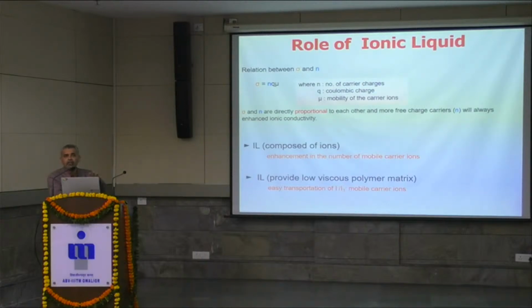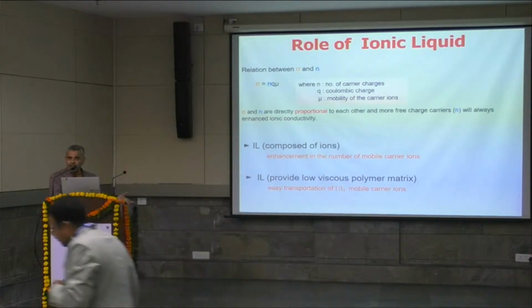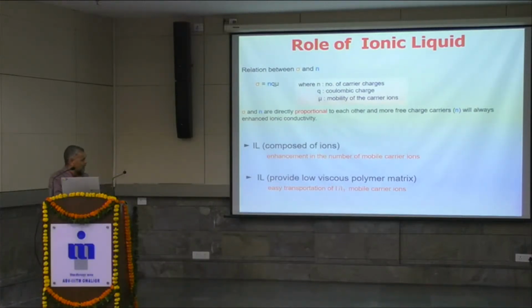If you put in ionic liquid, you get a more amorphous matrix. It means your mu is going to increase, and if this increases, your conductivity is going to increase. Because ionic liquid is composed only of cation and anion, whenever we put in ionic liquid, we found that this n value increases. So ionic liquid properties satisfy this equation, and we found that ionic liquid is a very good dopant for conductivity. It works as a plasticizer, reducing crystallinity, and along with that it provides more ions. So in both cases, conductivity increases.